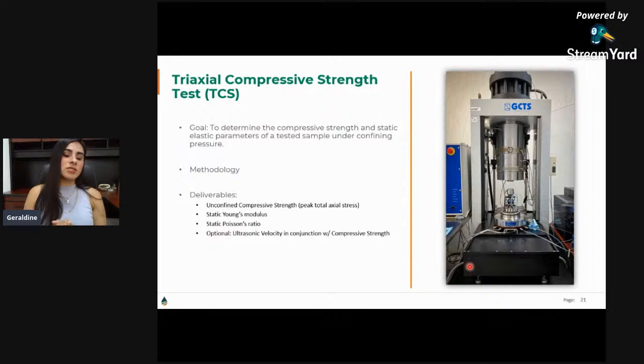The second one is the triaxial compressive strength test. It's similar to the UCS. It has the same goal, to get the compressive strength and also the static elastic parameters, but this time applying a confining pressure around the sample. It consists of the same thing: applying an axial load to the sample, but this time the sample is under confining pressure, and you will get the same data.